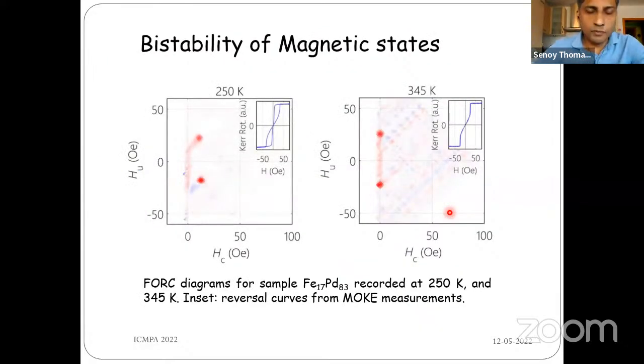Okay, so in order to gain more insight into the temperature dependent reversal process, we did first order reversal curve measurements using a magneto-optic Kerr effect system at different temperatures. Here is a summary of two different temperatures, T equal to 250 Kelvin as well as 345 Kelvin. At 250 Kelvin, one could see that the switching from the single domain to the vortex state involves an energy barrier, which is resulting in a hysteresis in the Kerr loop. However, if you increase the temperature to 345 Kelvin, then one could see a hysteresis-free switching. So basically, it means that now the energy barrier for switching from the single domain state to the vortex state is overcome by the thermal energy of the system.